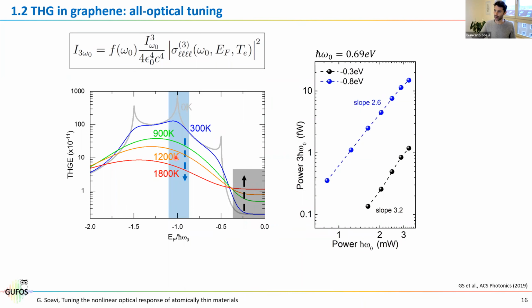Instead, if we look at this graph, so we go to large values of the doping, as we increase the electronic temperature, we decrease the efficiency. And now the idea is the following. If sigma 3, the conductivity, was independent from the electronic temperature, then as we scan the power, we should always see a cubic dependence.